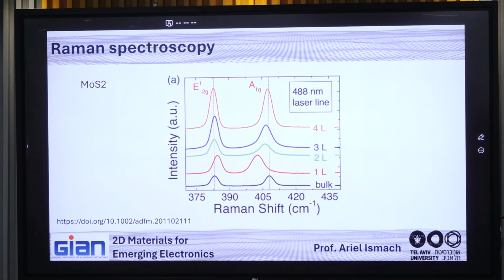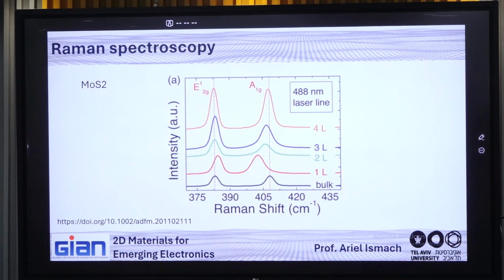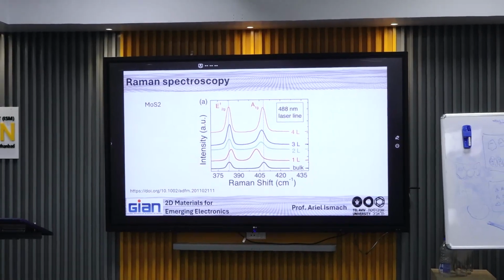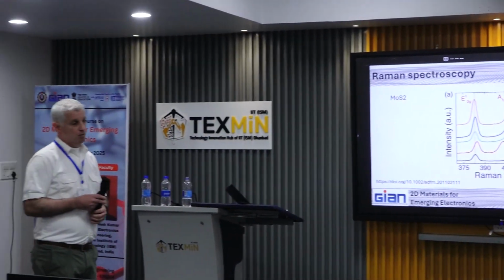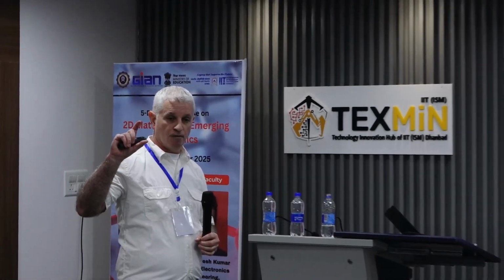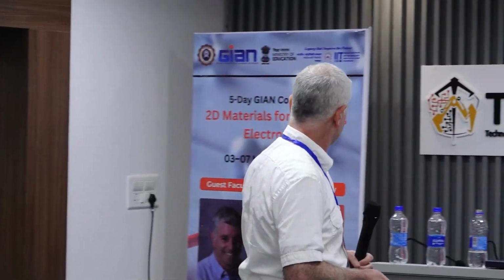By the way, the same in graphite, in graphene, and in MoS2, if you have defects, if you have impurities and a lot of other things, they may change the Raman spectrum in such a way that you cannot then be sure that you have a single layer, but you may have a single layer. For example, a very defective single layer will not give you the ratio of a high quality single layer profile. So therefore you need to also be careful with that.